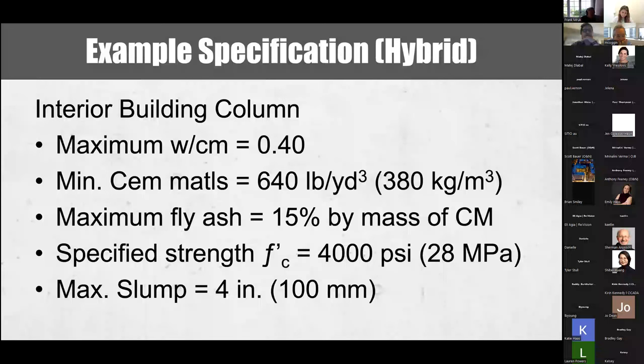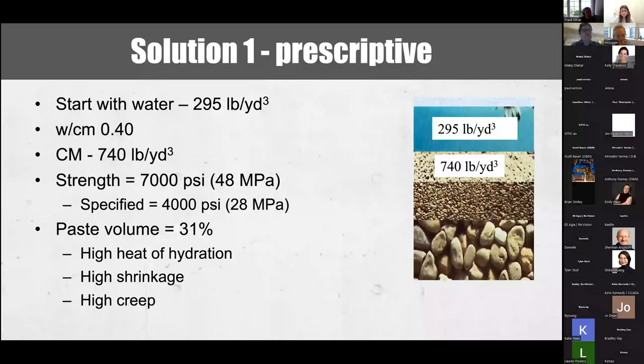The restriction on the water to cement ratio and slump will likely cause placement problems with congested reinforcement and likely result in surface defects due to difficulties with consolidation. One option is to start with water estimated at 295 pounds per cubic yard for the target slump, and with the local materials, and use a cementitious content of 740 pounds per cubic yard to meet the maximum water to cement requirement. The strength of this mixture is more likely to be in the range of 7,000 PSI or higher.